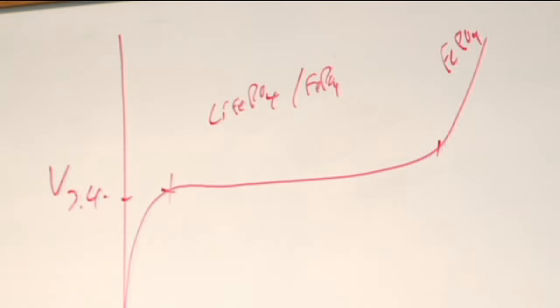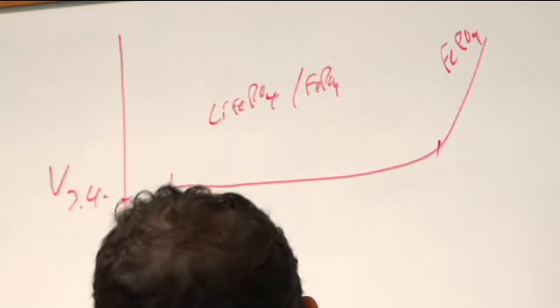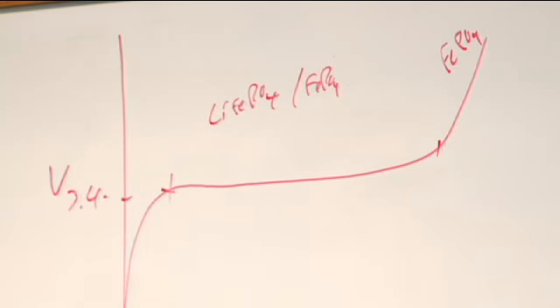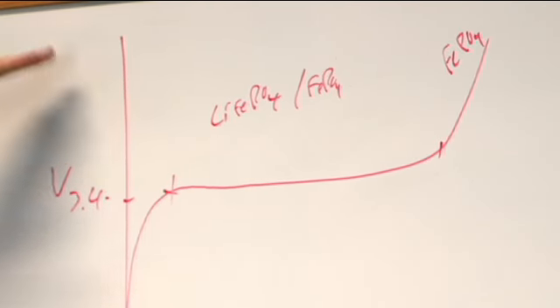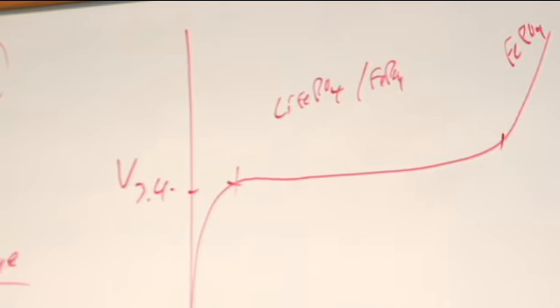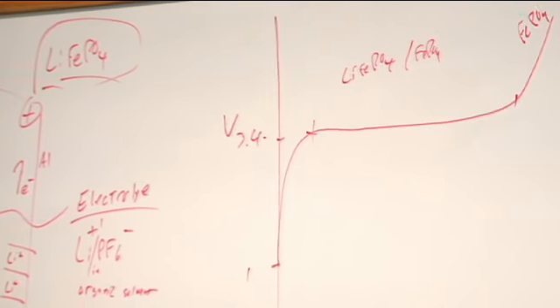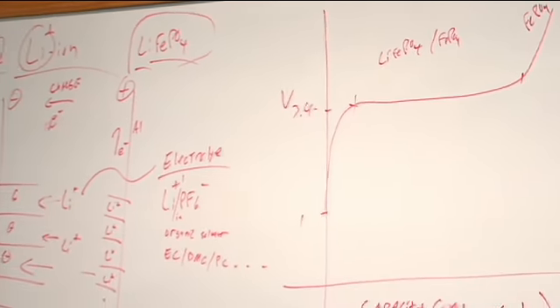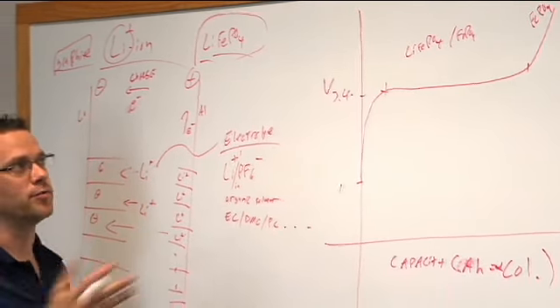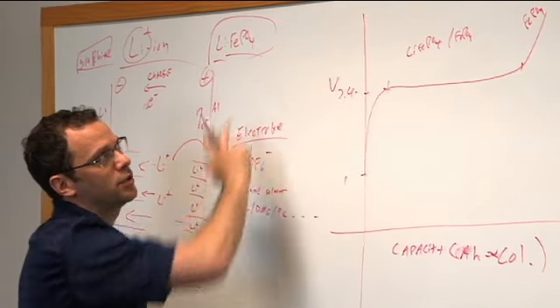Okay. Is this curve characteristic of all batteries? This curve is characteristic for only lithium iron phosphate. Lithium cobalt oxide, which is what we have in our cell phones and so forth, is more slopey, and it has a different kind of phase transition representation. It also has a plateau, if you want to call it that. It's more slopey in general, but it's more like 3.7, 3.8 volts, right? Which is good for energy, because of course energy is integrated power over time, and power is current times voltage. But it's not necessarily as good for safety.